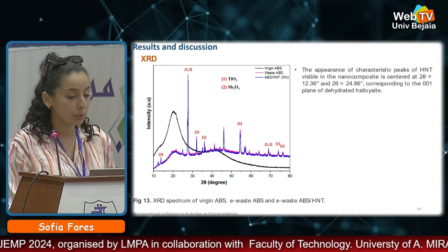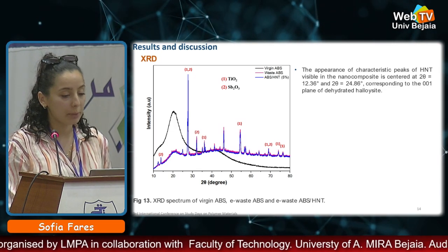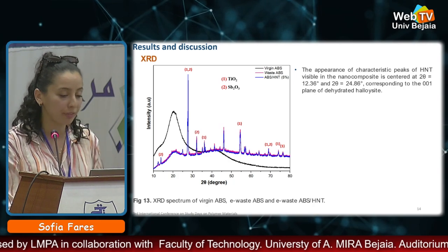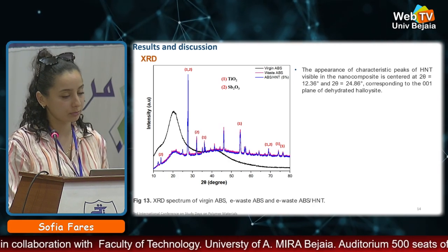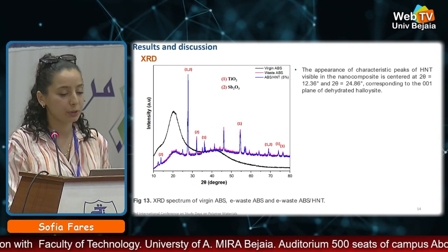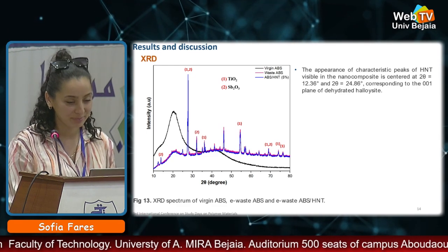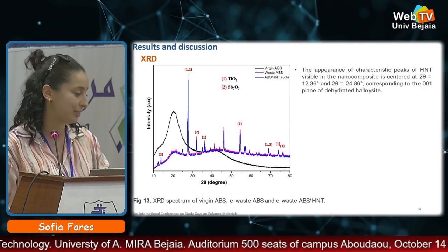The X-ray spectrum of the nanocomposite shows the appearance of characteristic peaks of HNT at 2 theta equal to 12.36 and 2 theta equal to 24.86, corresponding to the dehydrated halloysite.